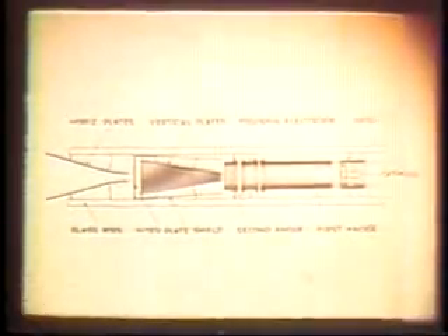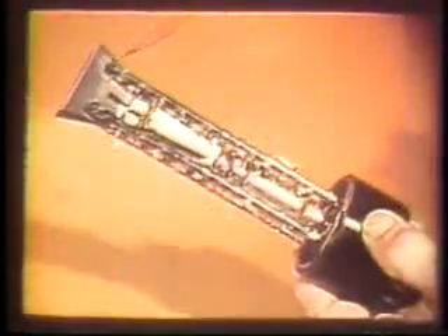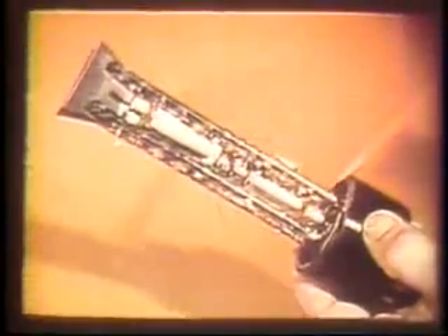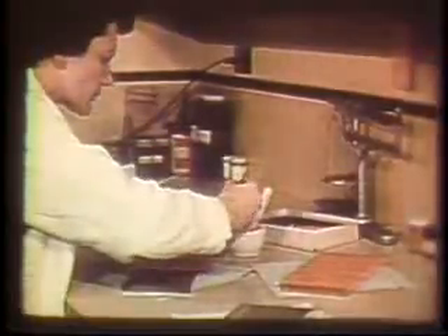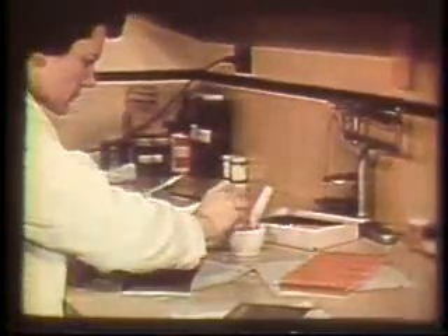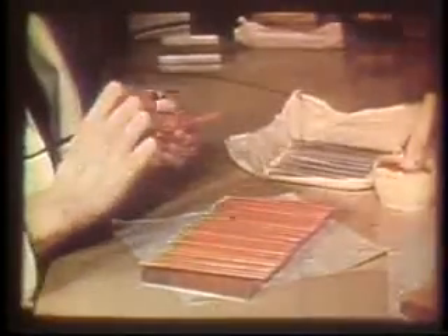One of the problems was that the Pyrex glass necessary to maintain dimensional stability is such a perfect insulator that charges tend to build up on the rods during operation of the tube, and sometimes cause distortion of the trace. We overcame this problem by lightly coating the Pyrex glass rods with a preparation containing lead oxide, which fuses into the glass as it is heated and forms a microscopic layer of lead glass on the surface of the rods.